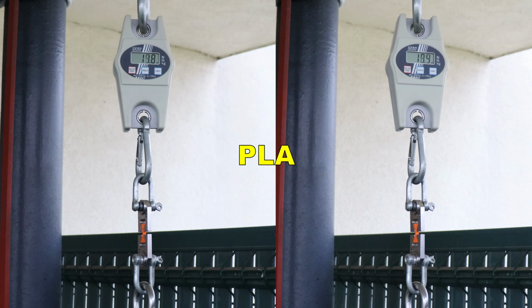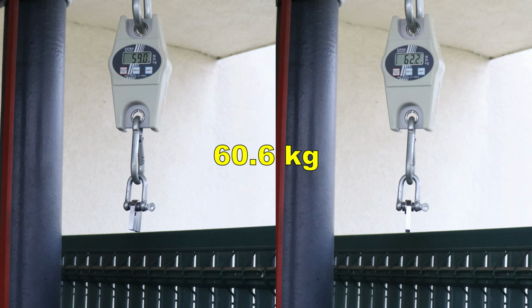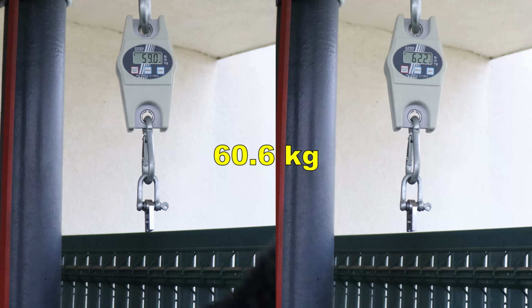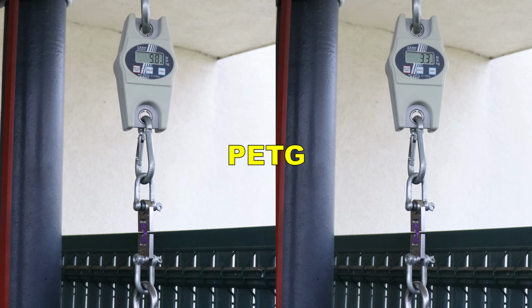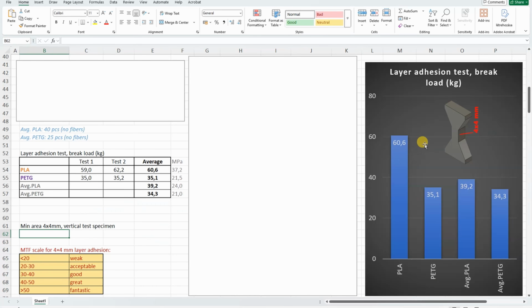Layer adhesion test, vertically printed objects, PLA and PETG. These PLA have fantastic layer adhesion. Here you can see my rating table for this test object. All other three are very similar. Now, an interesting thing I noticed, these high flow filaments will melt better and look like they will bond better to the layer below. So maybe this is the reason for the better layer adhesion. And it is nice to see this great value.